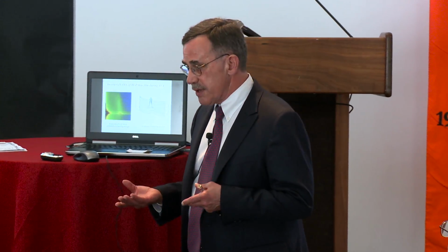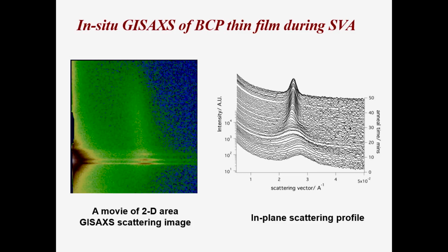And in the experiments that we've been doing, we've been using solvent annealing, and we're trying to characterize these structures in situ in real time so we can watch the development of these structures. So this is what the grazing incidence scattering looks like: you have the central beam from a synchrotron bouncing off a surface. And what we see are these reflections, which are characteristic of the average separation distance. And I can do a line scan across, so I can look at the intensity as a function of the scattering vector, which is the angle, if you will. So it's a classic scattering type of experiment as a function of time as solvent is being annealed.